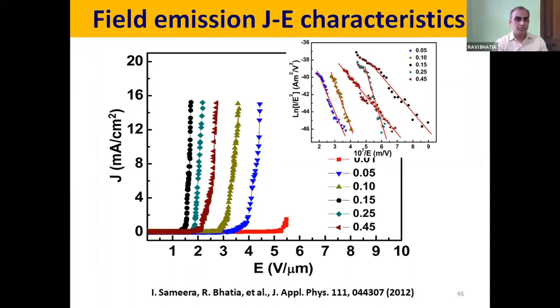So you just try to follow this curve and you will feel it interesting that the red curve belongs to 0.01 weight fraction. That means it is 1 weight%. So the 1 weight% sample provides you field emission of electrons after 5 volt per micron electric field is applied. So you keep on increasing the number of protrusions, that is the blue curve, 5 weight%. Here the field emission happens at an early stage, at 4 volt per micron. Very nice. We are improving the field emission properties with respect to the composite and filler loading.